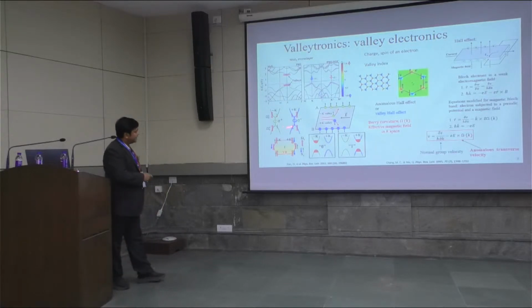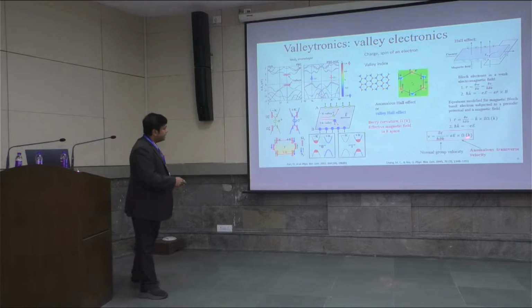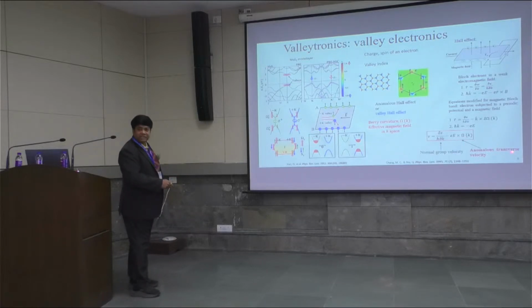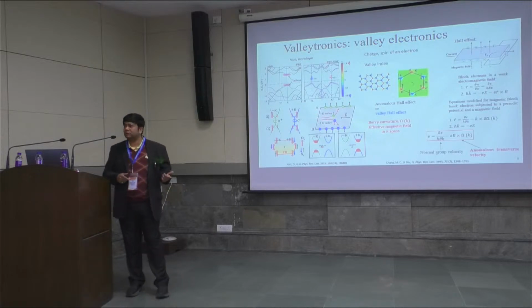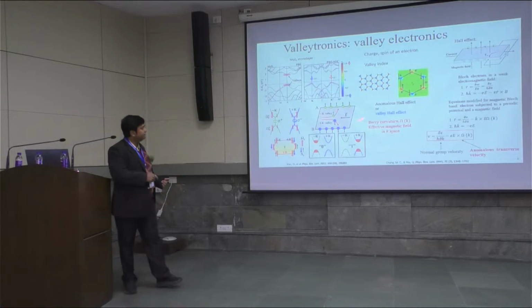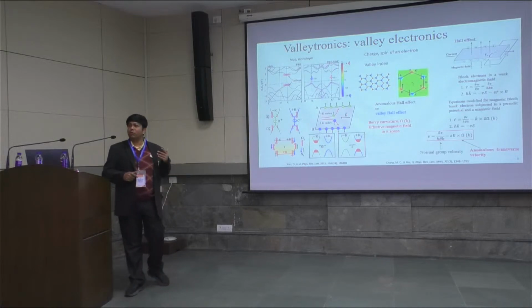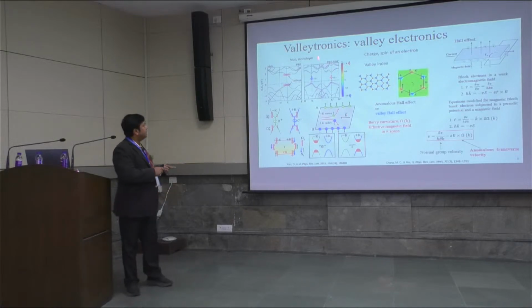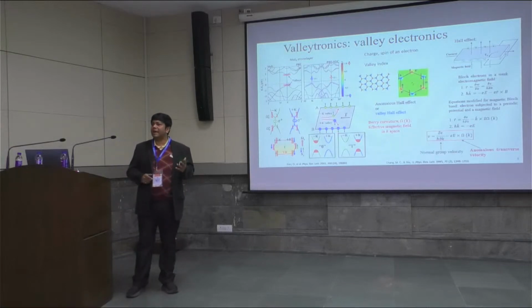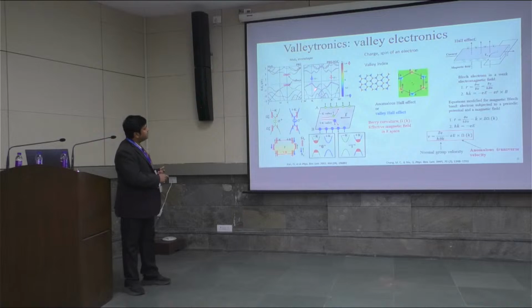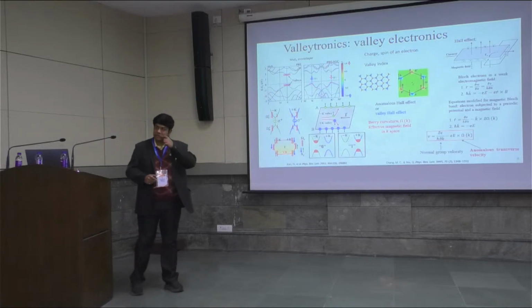The carriers in this valley, upon the application of the in-plane electric field, acquire an anomalous transverse velocity, and the carriers in this valley undergo a Hall effect, which is called the anomalous or Valley Hall effect. And very few materials are experimentally known which exhibit the Valley Hall effect. Those materials are mainly MoS2-like, which show a large Zeeman type spin splitting at the valence band and a very small splitting at the conduction band.